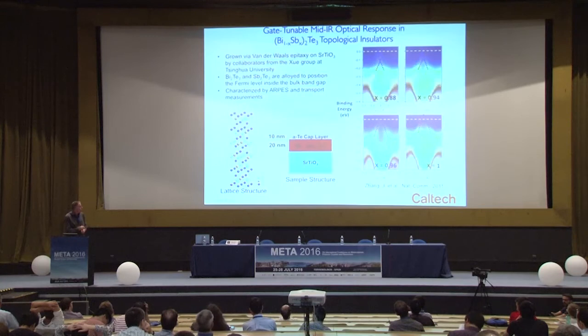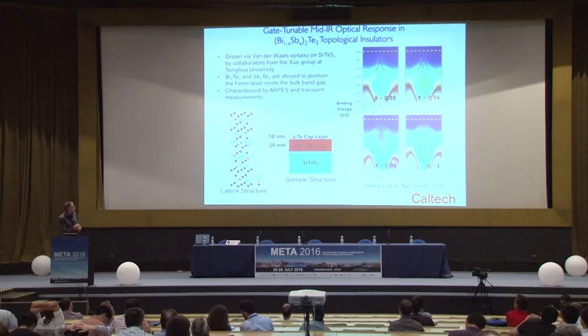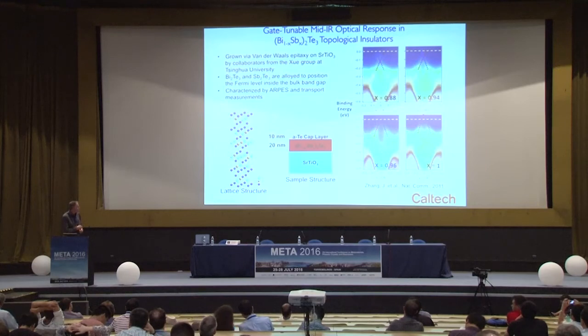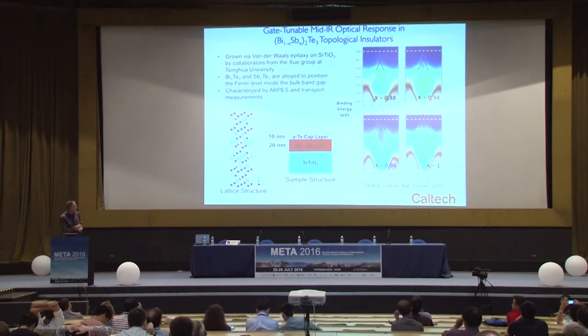And typically, in the growth of materials, we've grown materials here together with the Xue group at Tsinghua University. The position of the Fermi level is tuned by changing the band gap and the doping, by changing the composition in bismuth antimony telluride thin films. You can see here in an angle resolved photoemission the indications of the Dirac-like surface state that lies above the bulk valence band in this material.